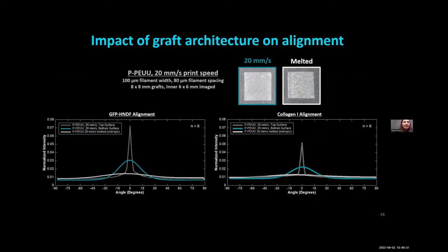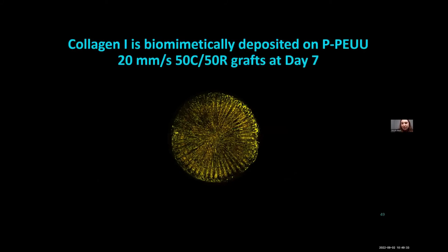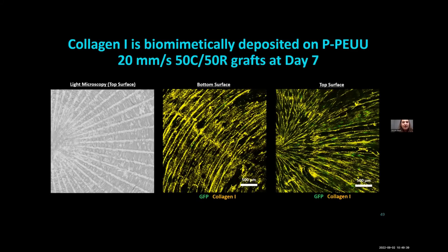And so you can extrapolate this beyond squares and create more complex architectures that can encourage cell alignment along more complex structures. So taking a circular and radial graft, for example, we can see on the bottom surface that's been printed in circles, we get this nice collagen and cell alignment in a circular direction, versus on the top surface of the graft that has been 3D printed radially, you can get this radial alignment here.